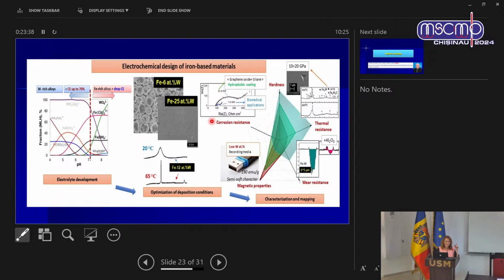But not always is it bad. Because you can apply this material for biomedical application. If you make a stent from this material, it will corrode with some speed, or you have encapsulated material, and you can bring this material inside a specific place, because it's magnetic also. So after corrosion, you can release the material there smartly.